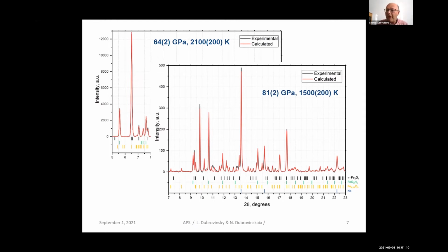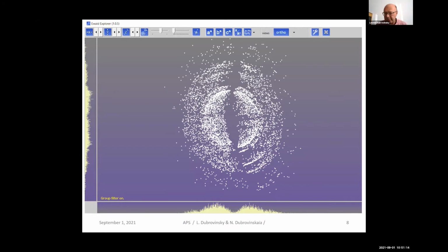So what we did, how we approached the problem, we used single crystal diffraction in the diamond anvil cell. I will not describe how we are doing this. First of all, most of you know what and how we are doing. Second, it's perfectly described in many different publications. Third, if you really want to learn this, you can just come to the IDD 13. And I believe that Stella will teach you in the next couple of hours, at least to the extent that you will be able to analyze some relatively simple cases on your own. This technique is already, I would consider it, established. We are using it, and this technique is spread over the community, even for samples which have been laser heated.